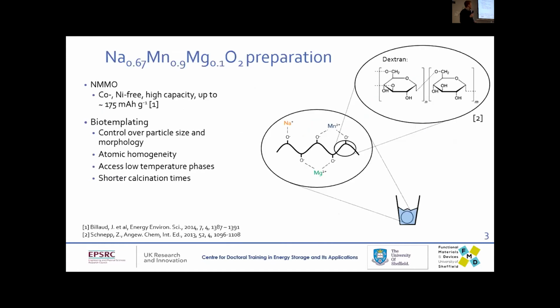So the material that I'm working on is this sodium manganese magnesium oxide, and there's a couple of reasons for that. One is that it's nickel and cobalt free, which is good if we're worried about sustainability. And the second, it has this high specific discharge capacity. So it's been reported that it goes up to 175 milliamp hours per gram, which is about the same level as today's lithium ion batteries.